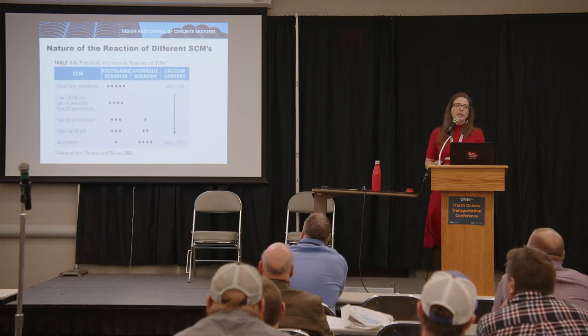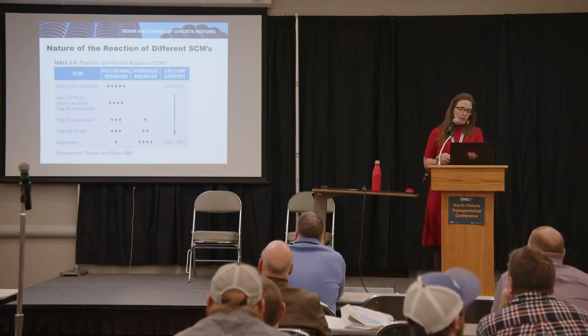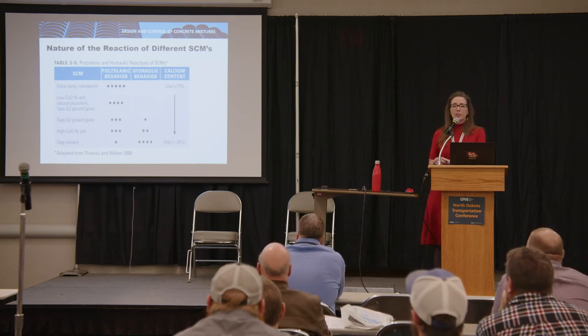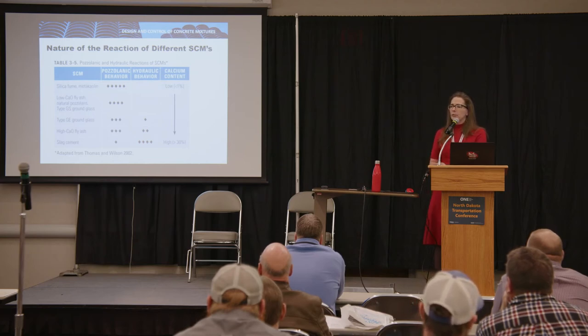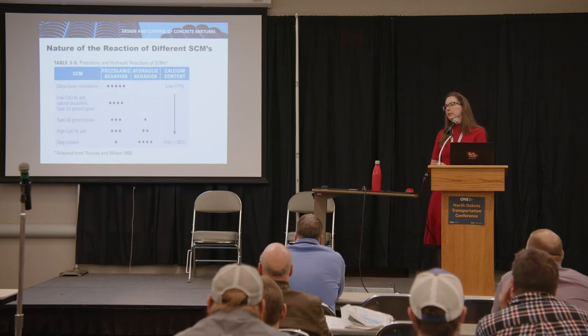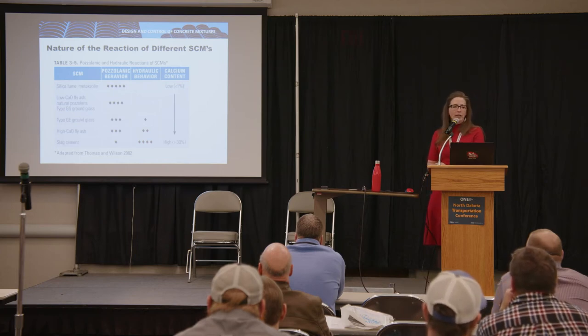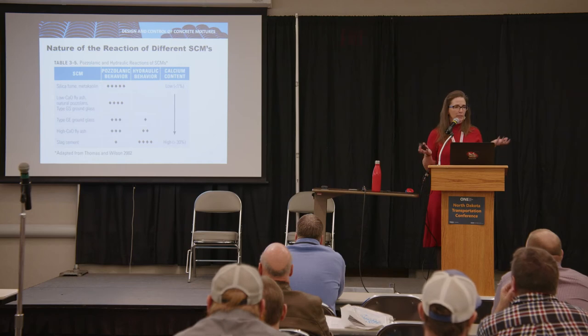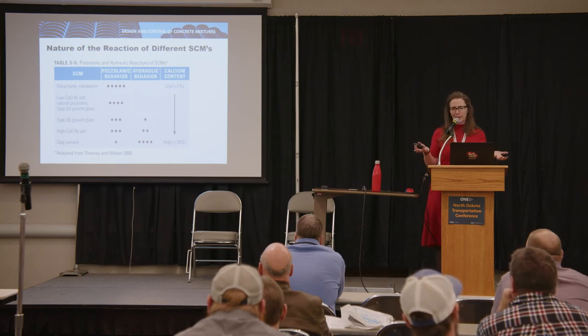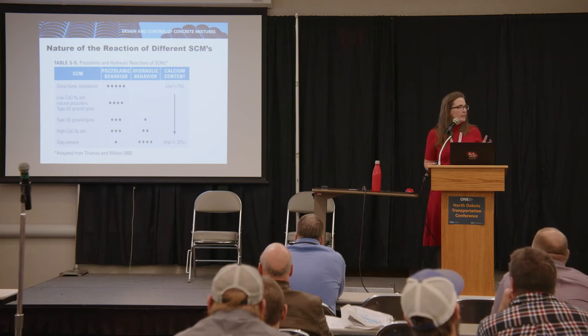And then we do hit in a separate chapter on supplementary cementing materials, but those standards are changing too. For years, we confused the heck out of our industry. We told everyone that what matters for fly ash is the silica and alumina content. We didn't mean it. We were just kidding. The whole time we meant calcium content, by measuring the silica and alumina content in the standard. So it was the messiest description, and now it's based on calcium content.